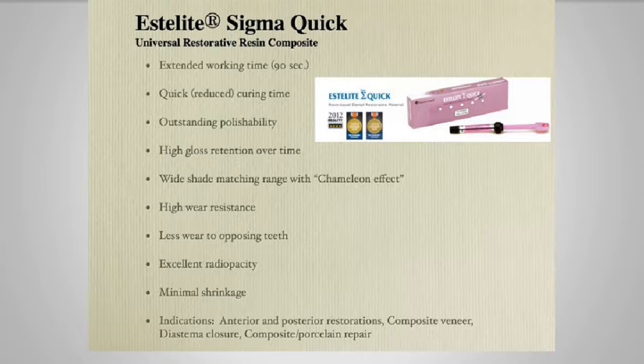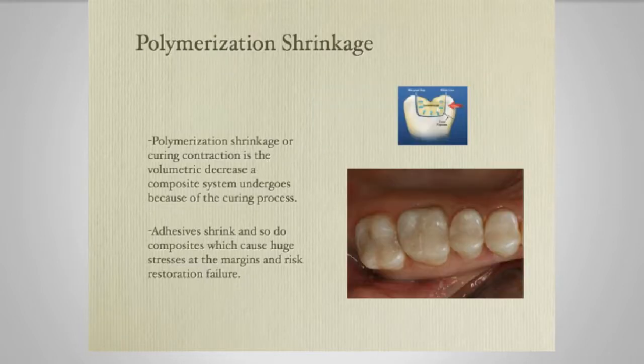So let's discuss polymerization shrinkage. Basically, this is the curing contraction that happens when you cure composites. During the polymerization reaction, the composite changes from viscous to viscoelastic to elastic. And when the composite develops an elastic modulus, the contraction becomes shrinkage stress. Now the stress causes the bond strength at the tooth-to-restoration interface to break down, and then gaps form and you get the loss of adhesion. When the loss of adhesion occurs, you get fluid movement, which causes sensitivity to the patient.